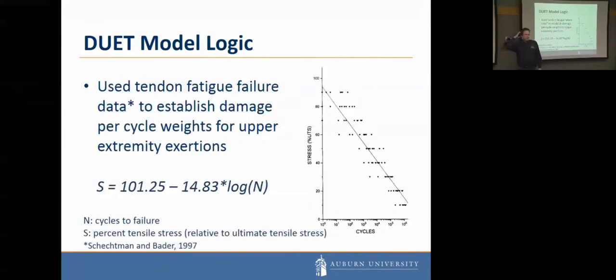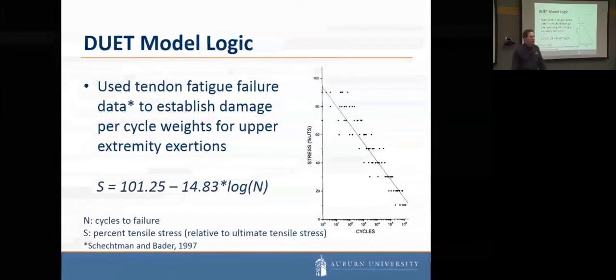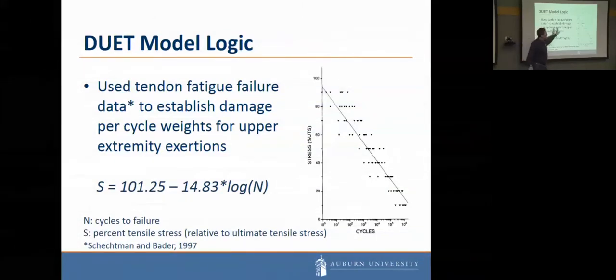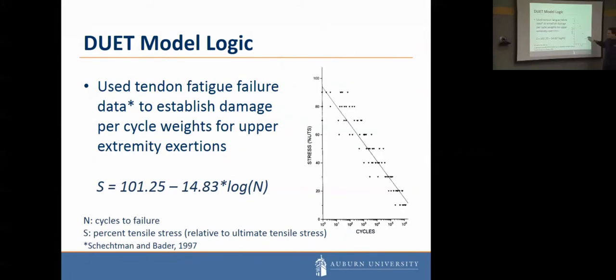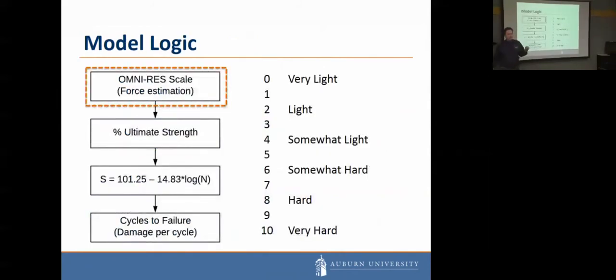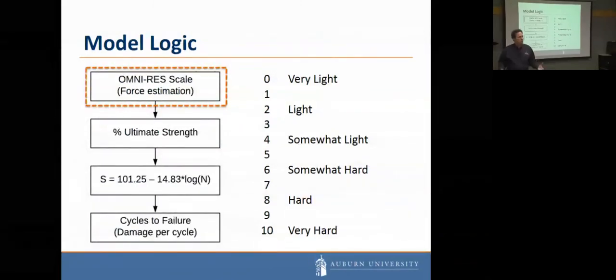Okay, we did a very similar thing with our upper extremity tool. And we used a very nice database that was developed by Schechtman and Bader back in 1997. What they did was develop a fatigue failure curve. This is a log scale, so it doesn't look like the same curve that I showed you before, but it's basically the same, looking at how tendons react to different levels of loading. So we used that data and an equation that they came up with, looking at the stress and the number of cycles. And we mapped that to different perceived exertion levels.